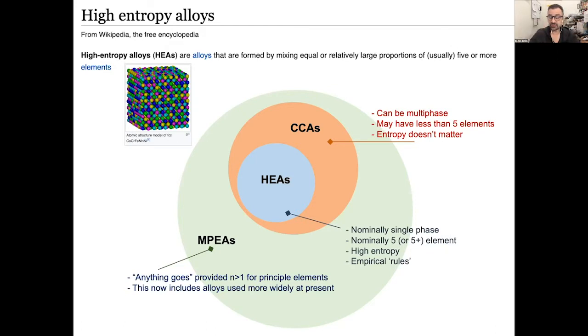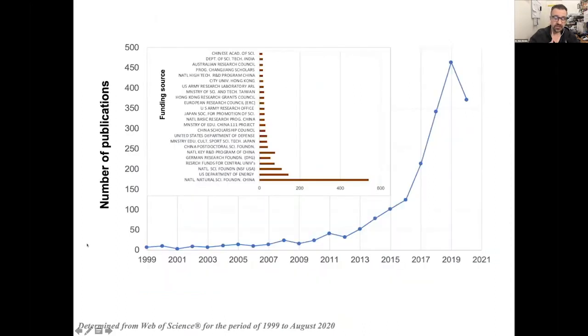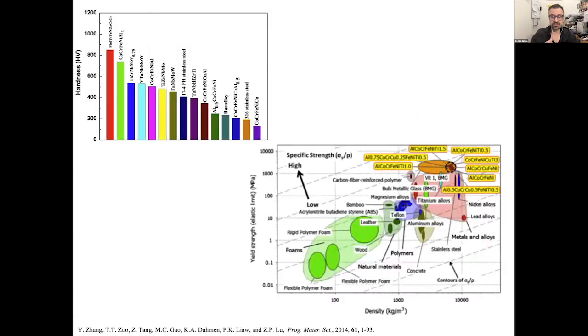There are some multi-principal element alloys that have been around for a very long time, particularly in the nickel alloy family. And of course, as Kevin mentioned before, the number of publications has just gone boom in the last decade for these particular alloy systems. And it's not surprising when you look at the physical properties. So if you look at the physical properties of these alloying elements, in the top left, you'll see extreme hardnesses. This is from a review from the team that Peter Liaw works with some years ago now. And on the bottom right, you'll see extremely high yield strengths. But what's interesting is these yield strengths are really coupled with high densities.